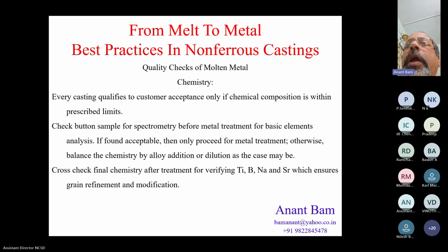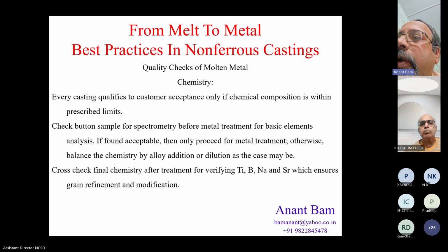Chemistry. Every casting qualifies for customer acceptance only if chemical composition is within prescribed limits. Check button samples for spectrometry before the metal treatment for the basic chemistry, basic elements. If found acceptable, then only proceed for metal treatment. Otherwise, balance the chemistry by alloy addition or by diluting, as the case may be. Cross-check final chemistry after treatment for verifying titanium, boron, sodium, strontium, or whatever you have added as metal treatment element. Sufficient percentage of titanium and strontium ensures grain refinement and modification. Next slide, please.